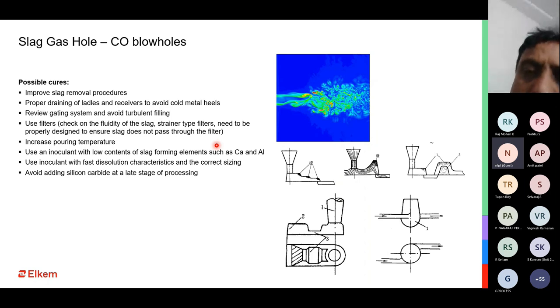Possible cures. The first possibility is definitely to make sure that we improve the slag removal. We need a sufficient and very effective way of removing the slag as late as possible before casting. We have to make sure that the ladles are clean, because the slag has the tendency to float up and accumulate around the rim of the ladle, where you have the metal coming in one after the other. So there is a strong possibility of this slag coming in from the previous treatment and getting along with the metal and going into the casting.